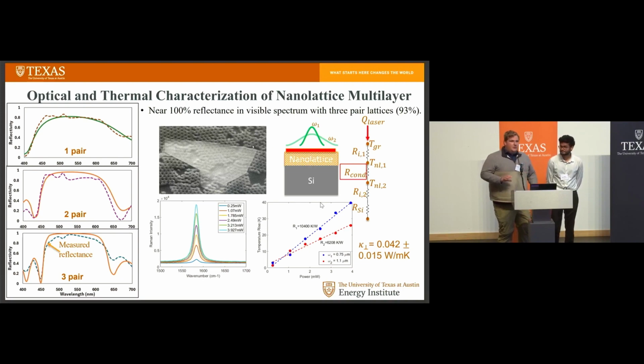So you can clearly see where there's that nice porous nanolattice that VJ makes for me, and then those little pores that are just the underlying lattice. We shine a laser light on it, and then based upon our extracted temperature and the laser power we are exciting the material with, we can extract a thermal resistance.